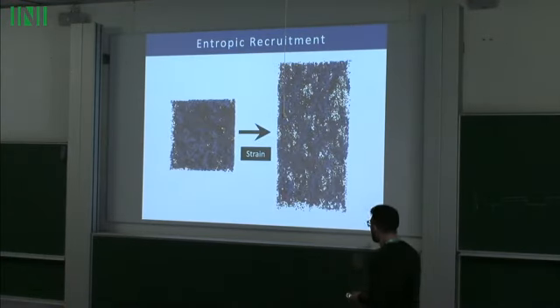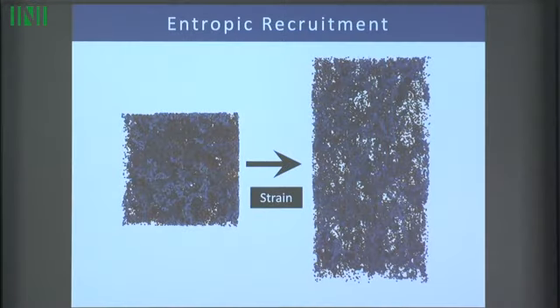Okay. So I don't have time to talk about this stuff, but we're doing some more detailed simulations where we take a really big three-dimensional full polymer network with reversible crosslinks. We put them into a box and we do a strain test, and we actually look at the spatial correlations of the permanent and reversible crosslinks. And we actually do find that there is some interesting behavior that it seems to be evidencing that there's clustering of the reversible crosslinks, and I have plots if anyone wants to see them afterwards.